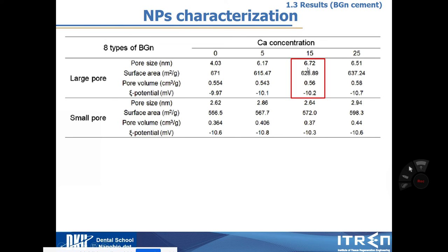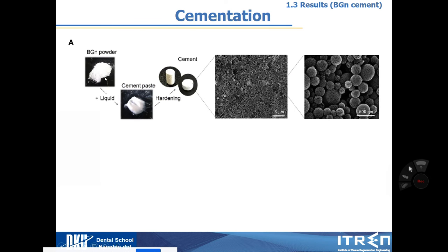as a future study, because I assume that more surface area, more pore size, and more pore volume give more good chance to have some cementation. And then I can successfully make BGn powder as a large pore, and after mixing in liquid, I can successfully show some hardening as a cement. When I look at their morphology by SEM microscope, you can see like this.